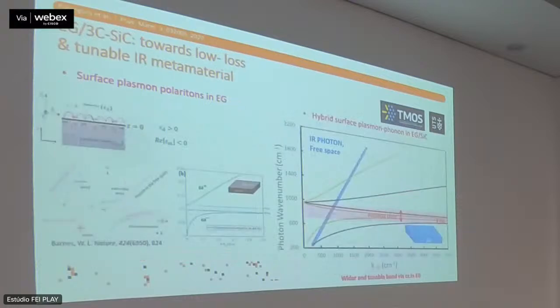Now, when you combine this with graphene, which is what we can do here, then what happens is, if you look at this dispersion curve, this is only the surface phonon response band of silicon carbide, and this would be like a photon in free space. And this is the responsivity of only silicon carbide. When you combine that with the plasmon that is supported by the graphene, you can extend the responsivity, but not only that, you can also tune it. So depending on the charge concentration, if you're able to tune it, you can move it up and down, depending on your charge. So this is extremely interesting.